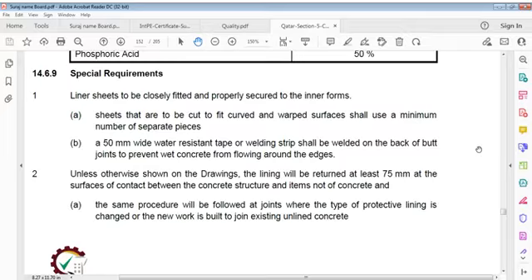Liner sheets to be closely fitted and properly secured to inner forms. Sheets that are to be cut to fit curved and warped surfaces shall use a minimum number of separate pieces. A 50 mm wide water resistant tape or welding strip shall be welded on back of butt joint to prevent wet concrete from flowing around edges.